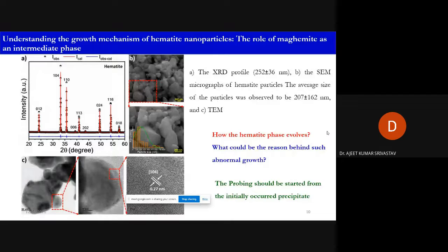So I'll not go into detail, but now we talk about the characterization, what we have observed after the synthesis. If you see the X-ray diffraction pattern, it's perfectly matching with the hematite phase. So phase is confirmed. Second point, if you see the scanning electron microscopy micrographs, we have larger sizes, but with a large distribution. Okay, so if you see the average particle size on the right-hand side, from SEM, that is 207 plus minus 162 nanometers. So size is large, but at the same time the distribution is also on the large side.